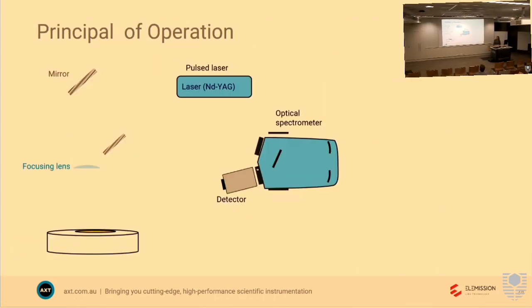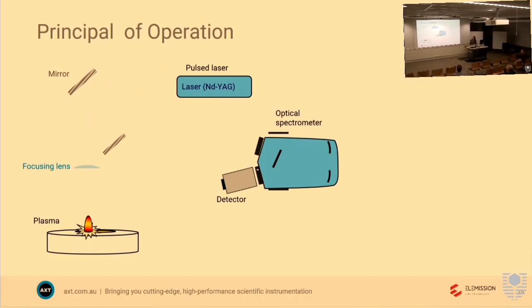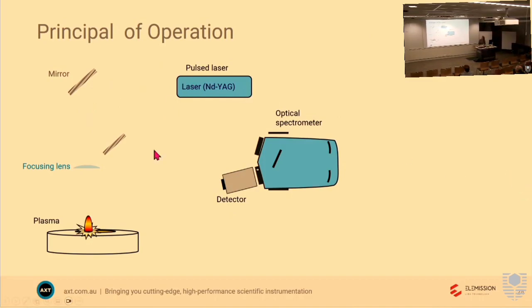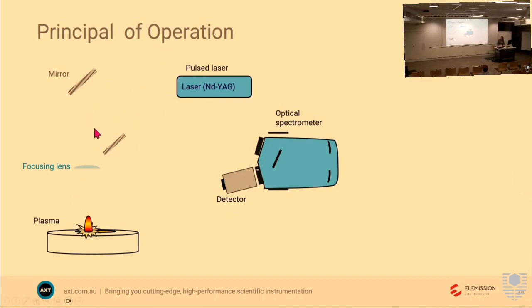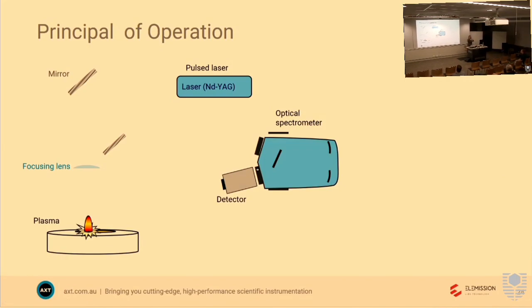The way a LIBS system works, it starts off with a laser, typically a neodymium YAG laser, 1064 nanometres. It goes through a series of optics and lenses, where it's focused onto the sample. So that laser beam starts off wide, and then it gets narrowed down, so all that energy goes onto the particular sample. It interacts with the surface of the sample, and you get a plasma.